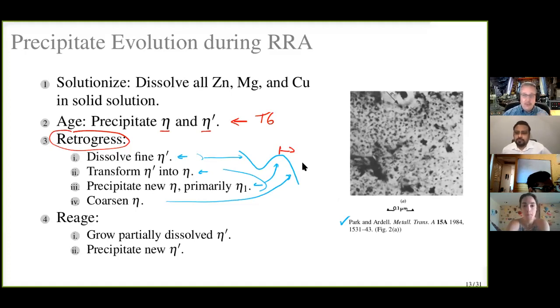Yeah. And that's one of the problems with forming these high strength alloys, because everything you try to do at elevated temperature can dramatically alter the heat treatment. And if you don't do it right, you have to go completely back to solutionization and reaging. And there's no way you can maintain the dimensions of your part by doing that. So it's a very intricate dance to get in between all these very complex processes that are going on. And quite frankly, it's part of the fun is figuring out that dance.